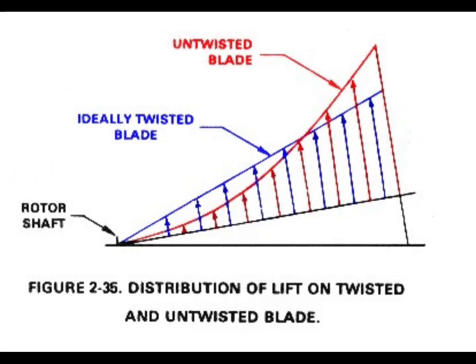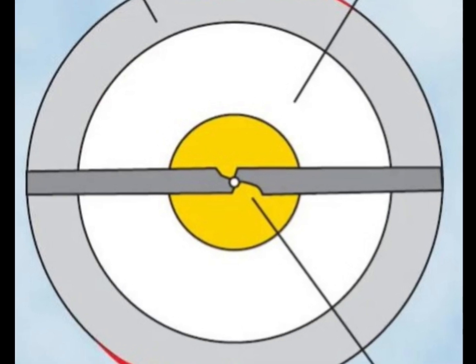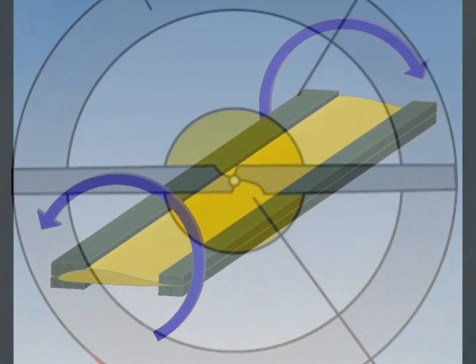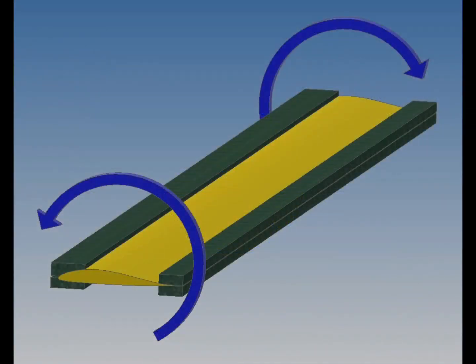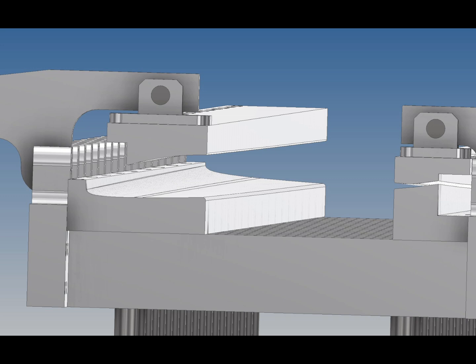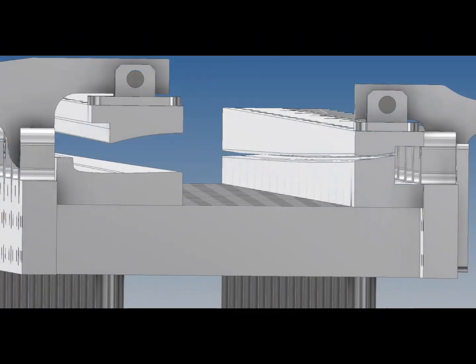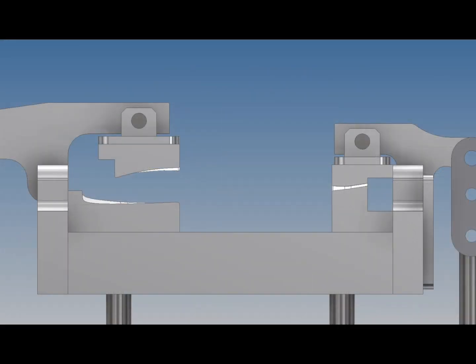Applying a twist into a set of gyro blades can have some very desirable effects. Among these is a more even distribution of the lifting forces along the span of the blade, and a reduction in the size of the stalled region at the center of the rotor disc, among other things. Other manufacturers in the past have imposed a twist in their blades by simply twisting the entire clamping section of their oven. We've taken this quite a few steps beyond that by actually 3D machining the true airfoil shape with the twist right into the inserts of the oven. Therefore, we can change the airfoil shape, we can change the amount of twist, and the location of the twists, all by simply swapping out these inserts.